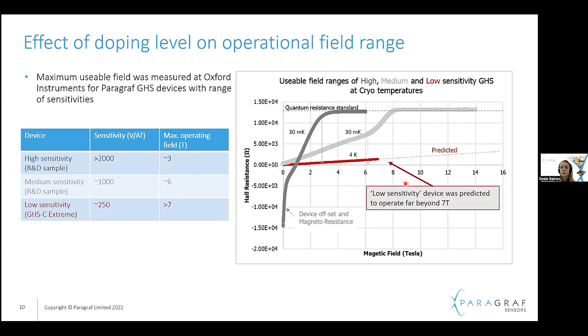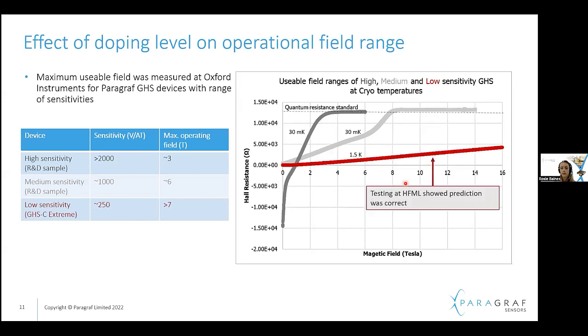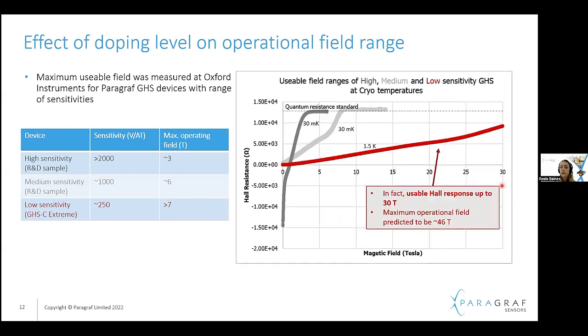So we did some more testing on this at HFML. Over a range of 16 Tesla, it's still looking very linear. Pushing it a bit further up to 30 Tesla, we're still seeing a very nice linear response over most of that range. In fact, it's still quite far from this first quantum plateau, so it could potentially carry on to around 46 Tesla.